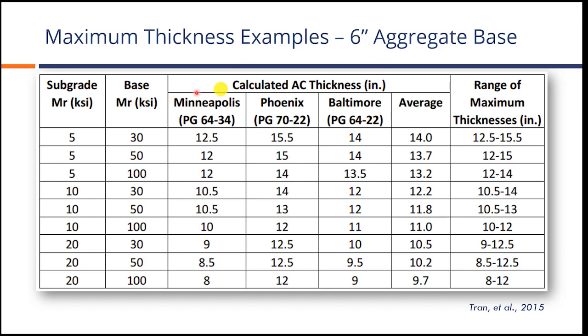So for example, we see base here, 6-inch aggregate base. We're changing the modulus of the base here over a range of conditions. And you can see the thicknesses that we came up with. And I just want to focus in over here on the range of thicknesses. So on the low end, over a wide range of conditions, we had 8 inches thick. And on the thick end, for the softest conditions here for the foundation, we came up with 15.5. And if you remember back to that first graphic that I showed you from Dave Newcomb, he had it around 8.5 to 14. That was a typical cross section. What we found here is a little bit wider, 8 to 15.5. But we're definitely still in that same order of magnitude range.